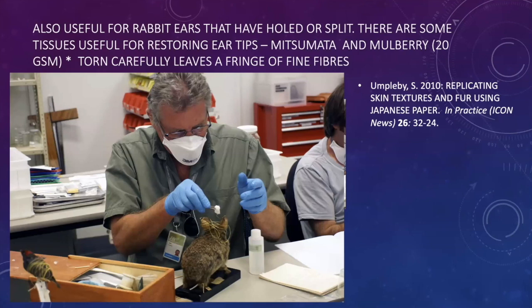All of these get damaged, pest damage particularly, and Japanese tissue will repair them, particularly if you have a really fibrous type of Japanese tissue, and Mitsumata is particularly good. Washi also, and mulberry of 20 grams per square meter. And if you tear it carefully, you can leave a fringe of fine fibers, which imitates the little marginal hairs that you get on mammal ears.